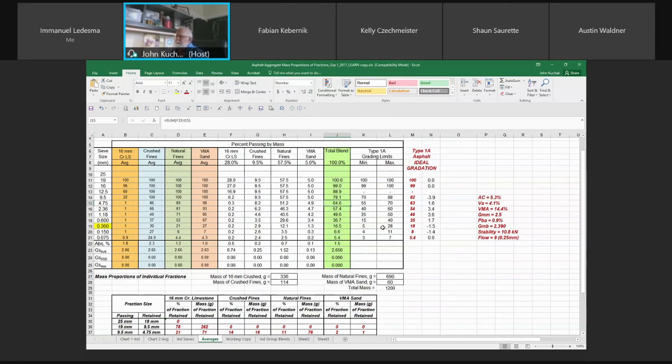And the 0.3, we found out that if you went right down the middle here, what would the middle be between 5 and 28? About 16. So we want to get that hump. We want to be a little finer. So I would try and get these as exact as possible. If 5 to 28 is 23, half of 23 is 11 and a half.